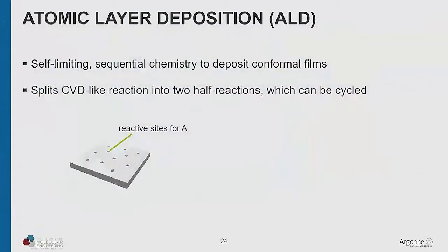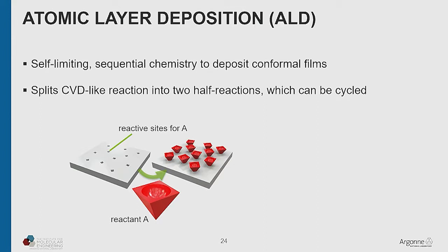So in atomic layer deposition, you have some kind of a substrate. Here I'm just representing it as a flat surface that has a finite number of reactive sites on it, which here are just represented as little holes on the surface. And what you do is you expose that substrate to vapor phase molecules, which here will be just represented as these red pyramids, which are designed to react with those reactive sites. So that vapor will flow over the surface, and those reactants will react with all those reactive sites and no more, because they can't react with anything else, so it's self-limited. You could flow it over the surface all day long, no more would deposit on the surface.